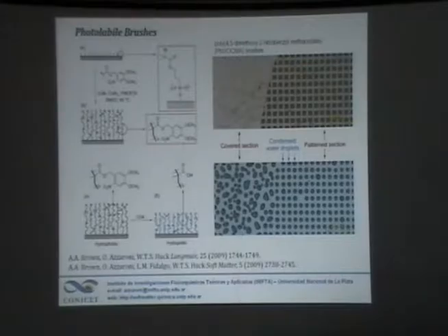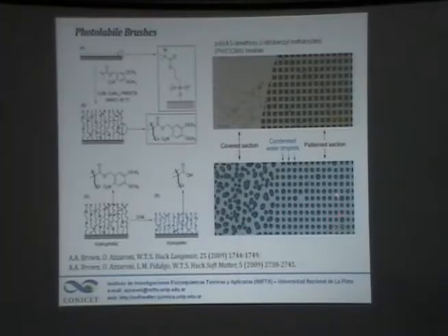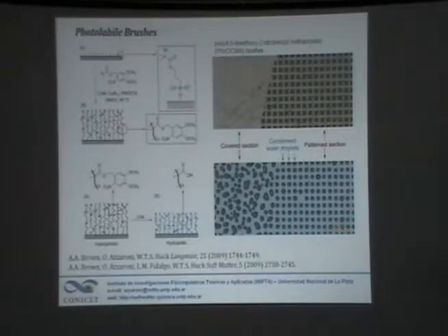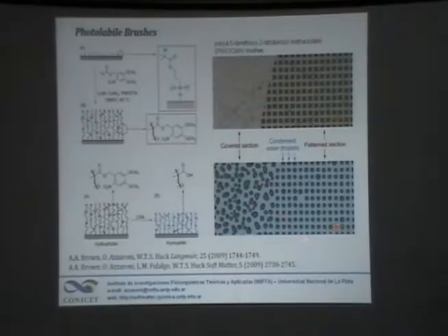We can use photochemistry — using light as a stimulus for transforming chemical moieties in the brush in a very controlled manner. We can use photo-labile moieties, shine light to cleave them, remove a protective group, and create a new chemical group which depends on pH. Depending on pH, this group is hydrophobic or hydrophilic. By using a mask and shining light, we create a polymer layer with alternating hydrophobic and hydrophilic domains. In a condensation imaging experiment, water droplets nucleate selectively in the hydrophilic domains, producing ordered droplet arrays.